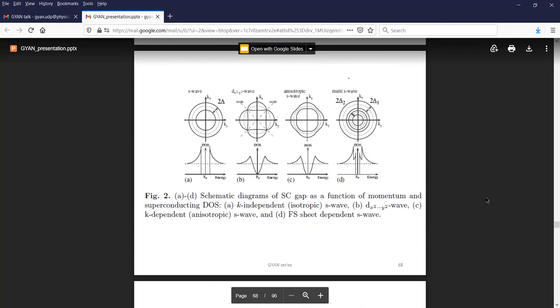It's now possible to measure the Fermi surface and then measure the superconducting gap as a function of momentum. In all the cases I showed before, they correspond to an S-wave gap where for all momentum it's the same gap value. For a D_x2-y2-wave symmetry, there are four nodes where the gap is zero. When you change the angle of measurement, the gap is maximum along the K_X and K_Y directions and at 45 degrees with respect to either of them, the gap becomes zero. One can also have an anisotropic S-wave where it's not the same gap value at all momenta but never has a node.